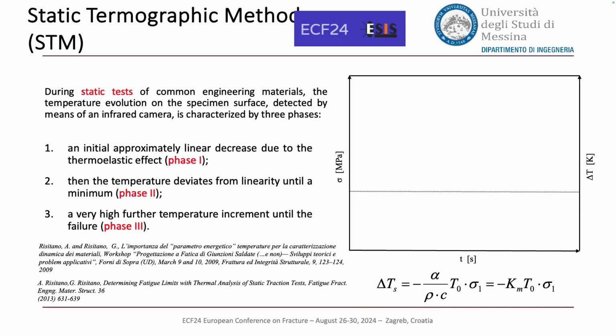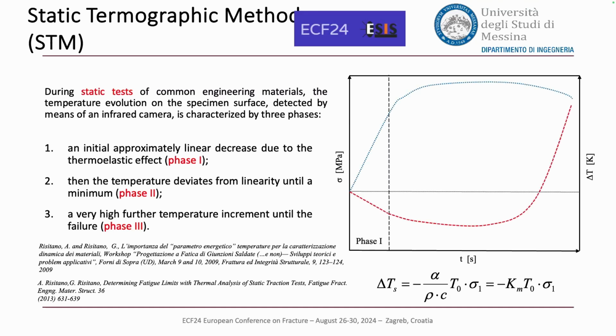Also, with the static test, we have the possibility to make a prediction about the fatigue limit of the material with the static thermographic method. During static tests of common engineered material, the temperature evolution on the specimen surface is characterized also in this case by three phases. An initial linear decrease due to the thermoelastic effect. Then the temperature deviates from linearity. And then a very high further temperature increment until the failure.